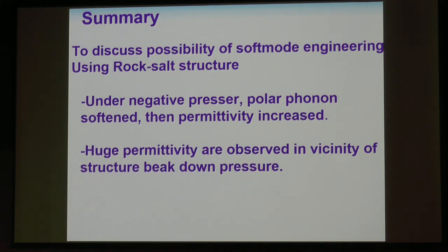So let me summarize my talk. We discussed the possibility of soft mode engineering using the rock salt structure. Under negative pressure, the polar phonon softens, then the permittivity increases dramatically. The huge permittivity is observed in the vicinity of the structure breakdown pressure.